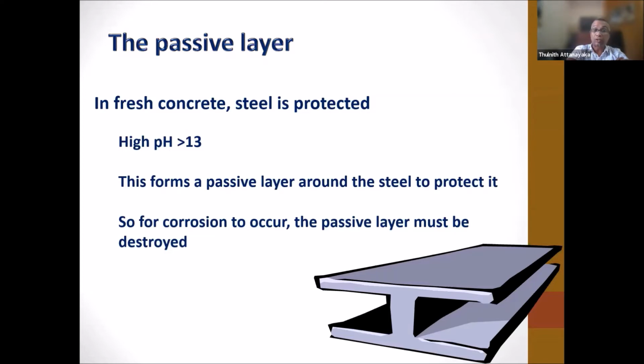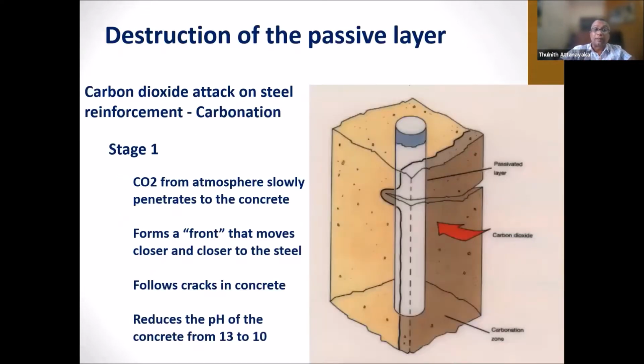So for corrosion to occur, the passive layer must be destroyed. I mean, destruction of the passive layer. Stage one of the carbon dioxide attack on steel reinforcement we call carbonation.